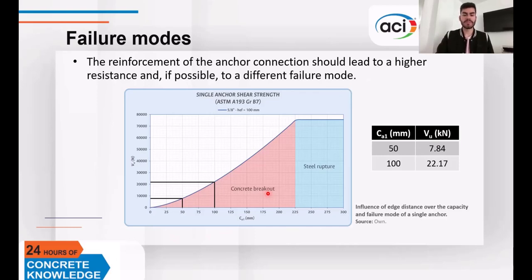Considering the previous parameters, this graph summarizes the behavior of a single anchor relating its ultimate shear capacity to its distance to the edge of the concrete member. As you can see, as we increase the distance, the capacity also rises. However, from one point onward, the capacity does not depend anymore on edge distance, but solely on the anchor's material properties. So the red zone corresponds to a concrete breakout controlled failure, and in the blue zone, steel rupture prevails.